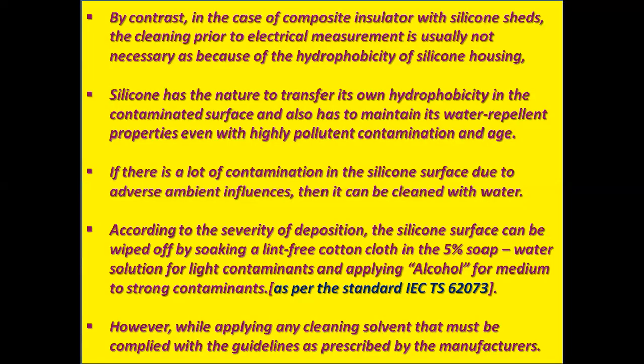Again, I repeat, according to the severity of deposition, the silicone surface can be wiped off by soaking a lint-free cloth in the 5% soap water solution for light contaminants and applying alcohol for medium to strong contaminants, as per the standard IEC TS 62073. However, while applying any cleaning solvent, that must be complied with the guidelines as prescribed by the manufacturers.